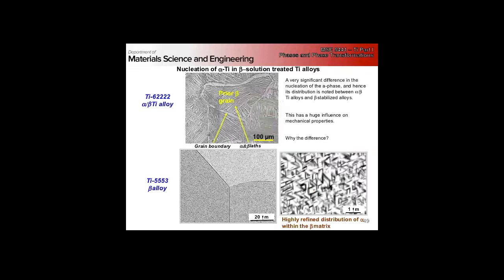So here's a typical alpha type structure. Here's our beta. We still have alpha, but it's on a much, much finer scale. Right. So huge influence on mechanical properties.